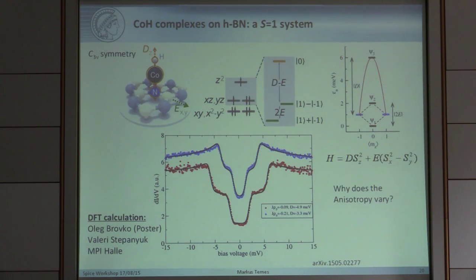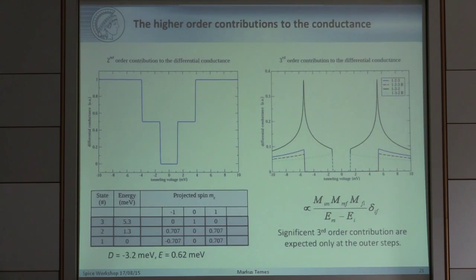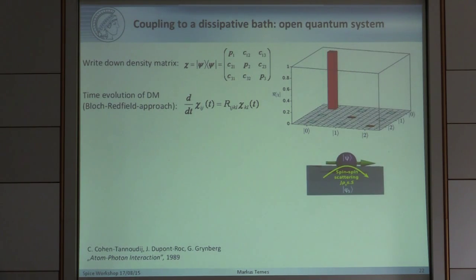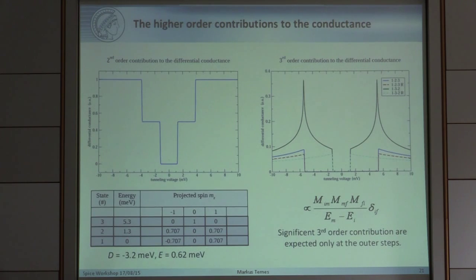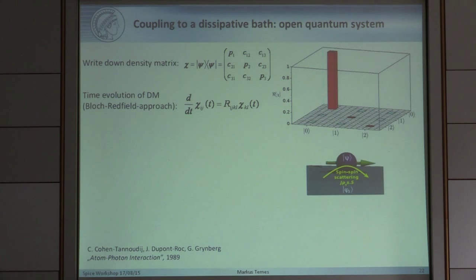And maybe at the end I can show you why all this happens also at the iron. Good. These peaks only exist where you see everything is cut off. If we don't have a bias here, then we have none of these excitations. So we are really in the weak coupling limit, and this means we can perfectly determine the coupling. And as Cyrus already showed you, now we just have to ask why it changes the energy.